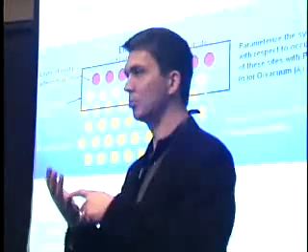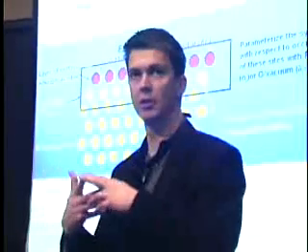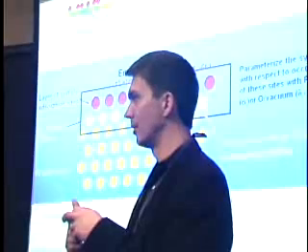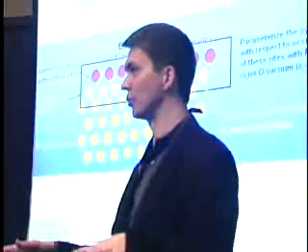But there's also a segregation thermodynamics now. On the surface, you may not have pure platinum. You may have either platinum or ruthenium. And the two interact. What segregates to the surface is influenced by what adsorbs. You may think of that as a quaternary problem, because platinum is in play, ruthenium is in play, oxygen is in play, and vacancies are in play, vacancies being vacant adsorption sites. But it's actually a 2 plus 2 problem. It's a binary configuration problem in the surface layer, and then a binary configuration problem on top of the surface layer. And so you can still perfectly solve this with a binary cluster expansion.